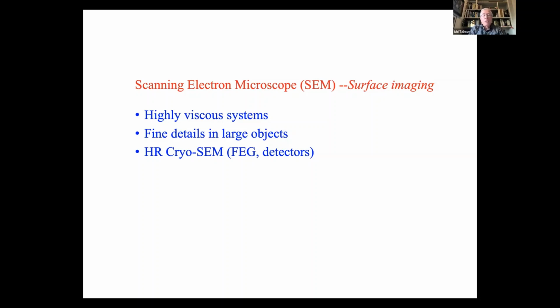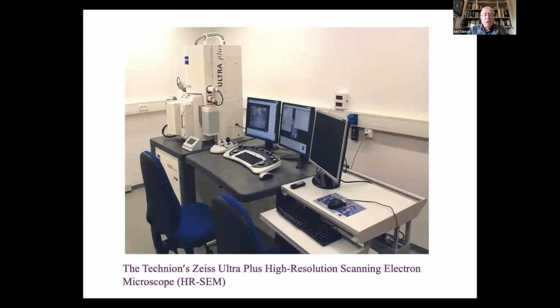type of instrument. And in this case, as I said, we use the scanning electron microscope, and nowadays we can use a high resolution Cryo-SEM, which has very sophisticated detectors and a field emission gun for emitting the electrons, with the advantage that we can use very low acceleration voltages of about 1 kV, which is very useful for our microscopy. This is how the instrument looks. It looks much smaller, again, for reasons that I'm not going to go into. And let me just show you a couple of examples of what we can do.